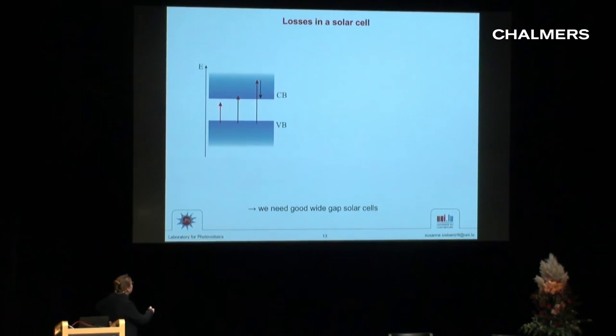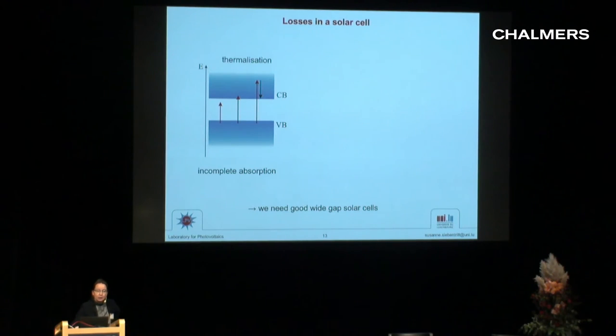And you need to find this compromise because of these losses. If the energy of the photon is smaller than the band gap, it's just going to go through, and you're going to lose it. If the energy of the photon is higher than the band gap, you're going to lose part of the energy, because the electron will be up here and then very quickly thermalize to the band gap, and we will lose this part of the energy. These competing processes give us the Shockley-Queisser maximum that Joseph showed.